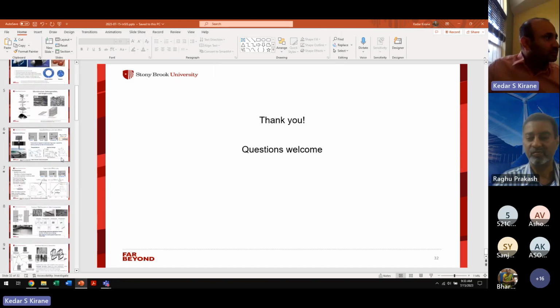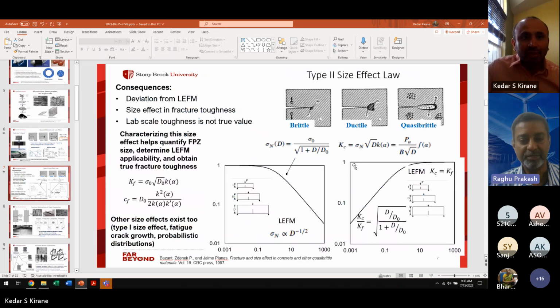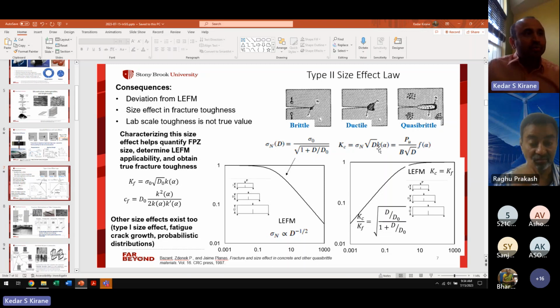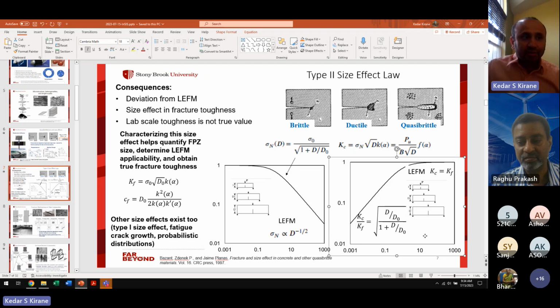Okay, let me open the slide. The slide is visible, right? Okay, if you look at the definition of fracture toughness, Kc is equal to sigma n times square root d times k alpha. If you flip it in terms of sigma n, the d goes on the other side in the denominator. On the other hand, if you start from the size effect law, sigma n is equal to sigma 0 divided by this. For sigma n, if you substitute the equation for Kc, you can derive this equation for Kc, where if you plot it, there is an increase in fracture toughness with size.